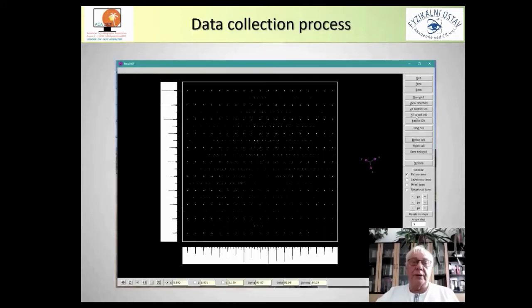The first task during the data collection process is finding the orientation matrix, cell parameters, and modulation vectors. For this, we can use programs which are supplied with the diffractometer, which means for Bruker system or for Oxford Diffraction system, we have some software which is very similar to what is presented here, but here I'm presenting something from Jana 2006. You can see from this diffraction pattern after fast handling of reflections that except for very strong reflections, we have some additional reflections which are much weaker. You can also see that in this direction we have this position somewhere between these two main lines, but for the second line it's almost 1/3, but not exactly.